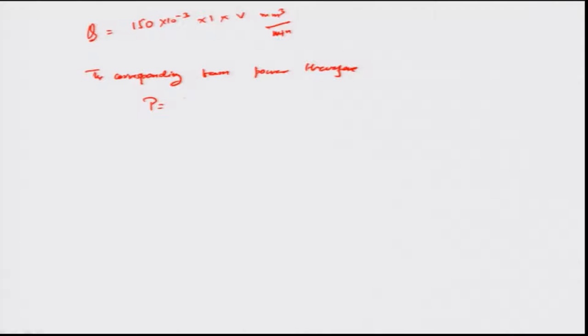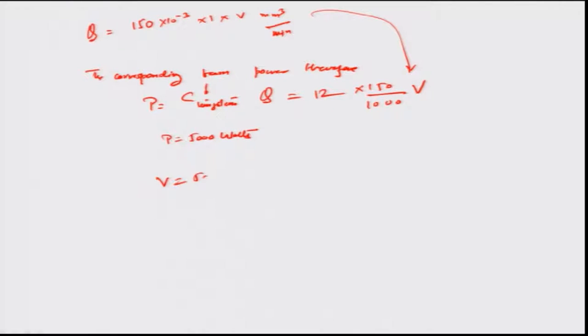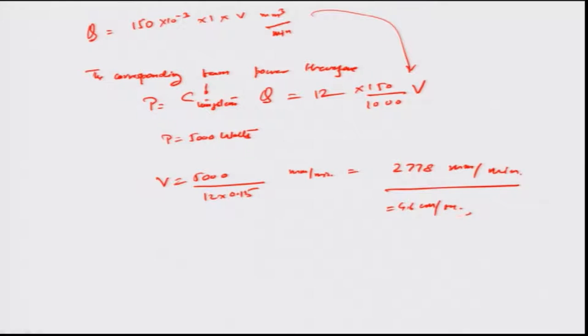will be given by P equal to C for tungsten, the material being cut here, times Q. The C for tungsten is taken as 12 watts per millimeter cube per minute, times the number of millimeter cube per minute predicted in the earlier step. Since P is given to be about 5000 watts, V becomes equal to 5000 divided by 12 into 0.15 millimeters per minute. So you can see the scan rate is about 2778 millimeters per minute, about 4.6 centimeters per second. That's how the beam scan rate can be estimated.